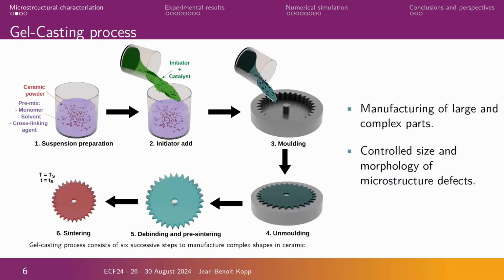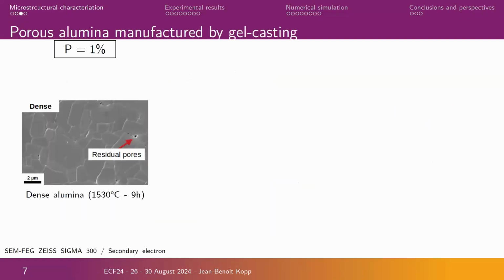So about the microstructure and the manufacturing process, we use a gel casting process with an industrial collaborator. So it was possible to manufacture very complex geometries. First of all, we have a preparation with ceramic powder, of course, and polymers to obtain a specific microstructure. In our case, we would like to control the size and the morphology of the microstructural defects. And in our case, it was porosity. So after molding and sintering, it was possible to have dense ceramics with a specific mechanical behavior.